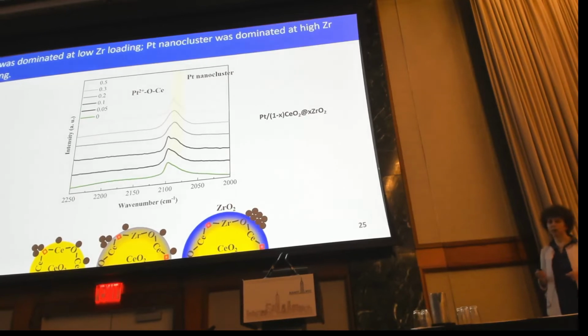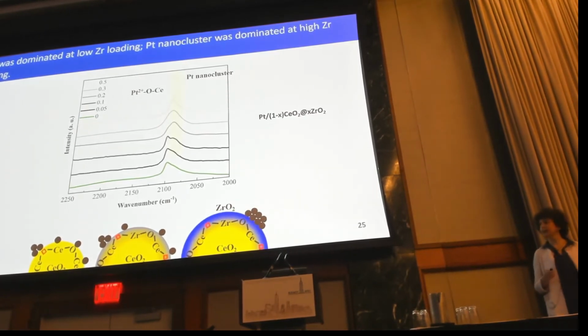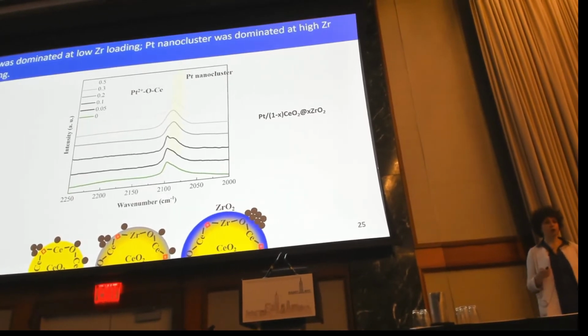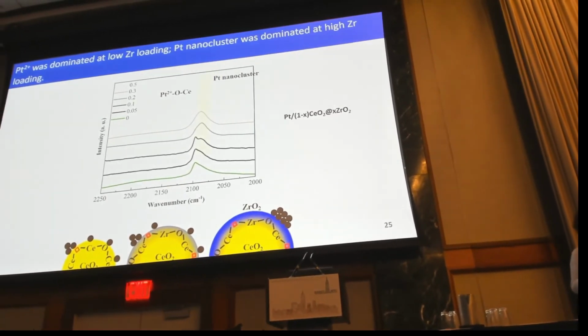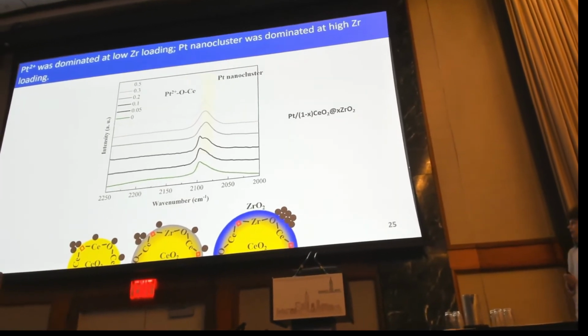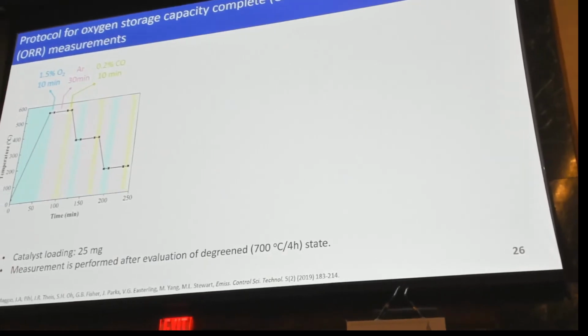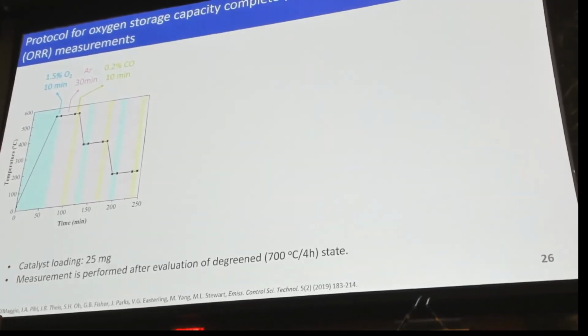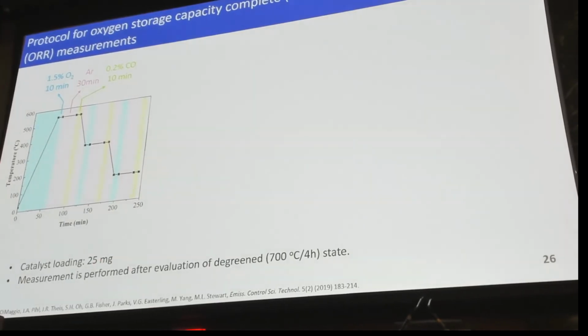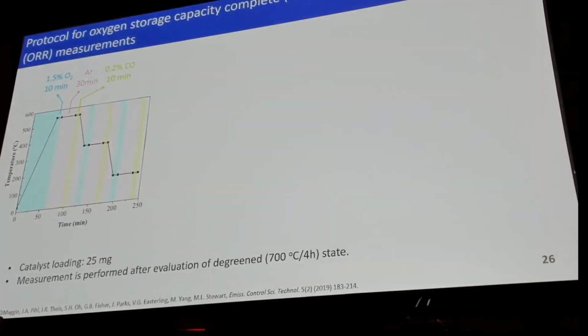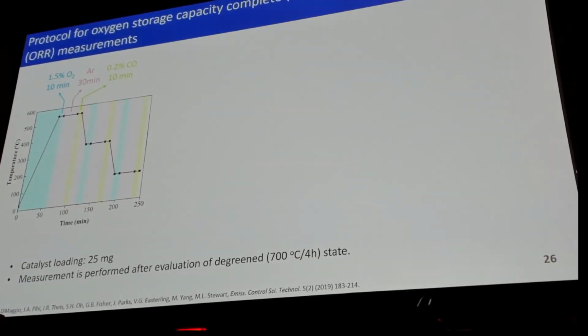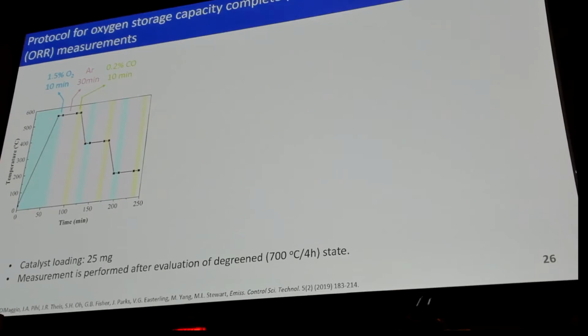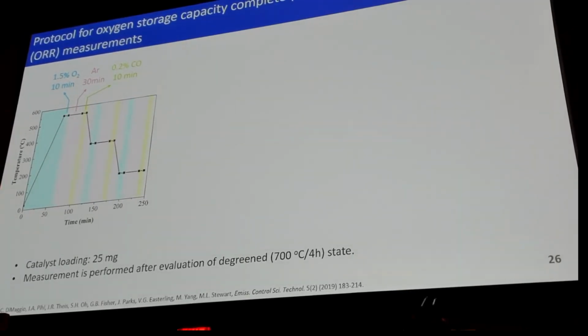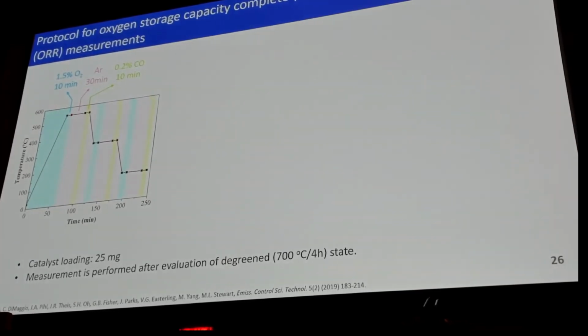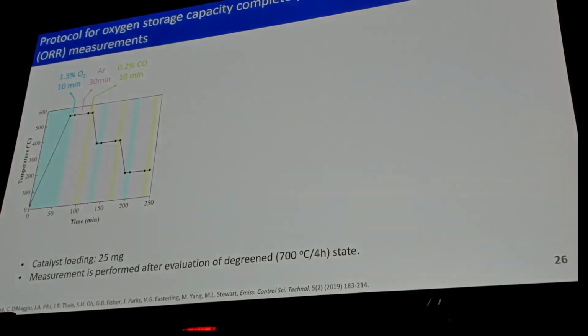Okay, so one important characteristic of the ceria-zirconia materials is the oxygen storage capacity and the oxygen releasing rate. And we want to see how these two parameters are related with zirconium content. So we found the oxygen storage capacity by an experiment that I'm describing here. The reactor is loaded with 25 milligrams of catalyst, and the catalysts in this case are in the degreened state, so they are not the best catalysts. Initially the catalysts are exposed to 550 degrees C with oxygen for 10 minutes. Then we purge out with argon for 30 minutes to make sure we remove the dissolved oxygen. And then we introduce CO for 10 minutes in the reactor.